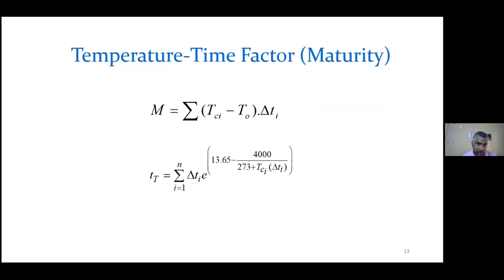And this slide shows you the maturity or temperature-time factor. As per the American standard, the first equation comes from the ASTM code. There, M is equal to the summation of (Tci minus T naught) into delta T. Tci is the temperature of the concrete at a particular instant, and this T naught is a datum temperature in degree centigrade, and delta Ti is the time step. I'm going to show you a plot for better understanding.